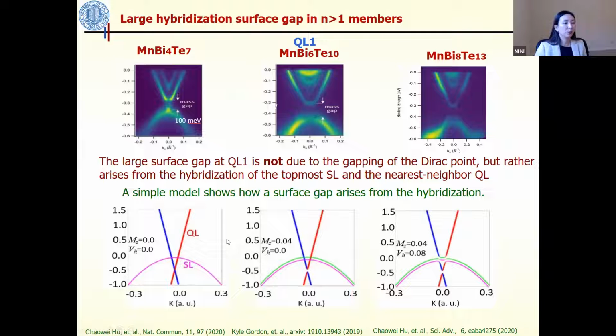We can see this from a simple toy model here. MZ is the Zeeman splitting energy, and VH is a parameter describing the hybridization strength between the QL1 layer and the SL layer. At MZ equal to 0 and VH equal to 0, what you have here is a Dirac cone, and then this purple band, which is from the SL layer. When you turn on the MZ, the Zeeman splitting energy, there is a gap on your Dirac cone. So you gapped your Dirac cone.